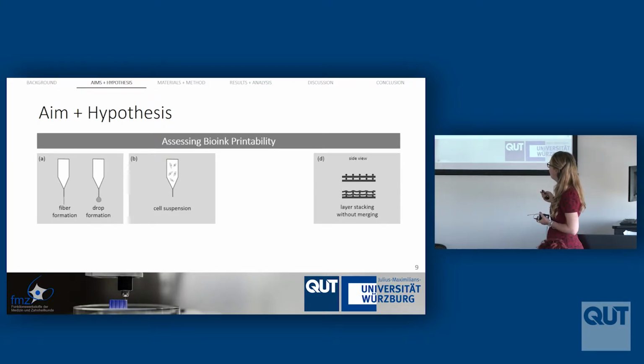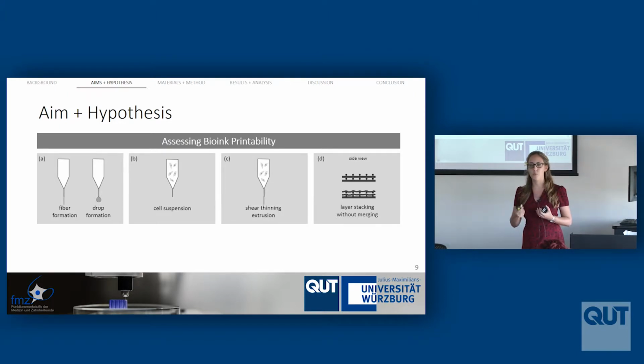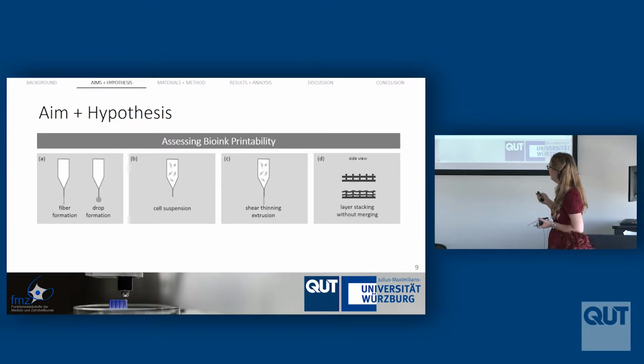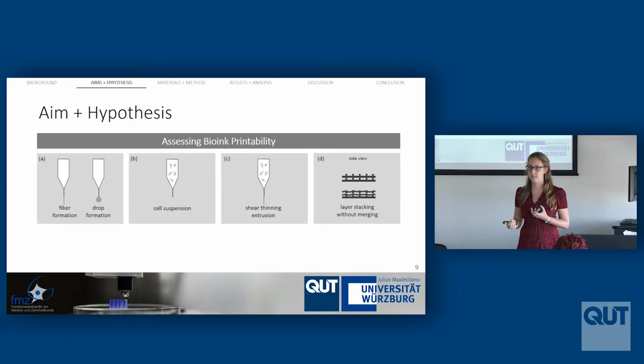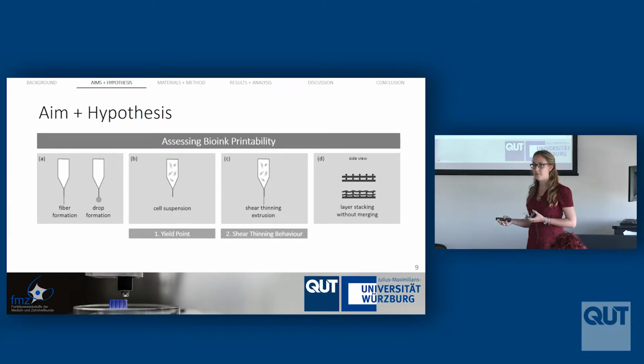And so a property of hydrogels is that they're shear thinning, and so this means that they get more liquid, so they get less viscous as you apply force to them. And so this is what happens through the needle. They start getting less viscous, and this allows the cells to move through the needle without being damaged, but then also be extruded into a fiber at the other end as well. And so the aim of my study was to characterize the yield point and the shear thinning behavior. So these are rheological properties of these materials, looking at their viscosity and their elastic behavior. Characterize these with some very simple, easy characterization techniques and be able to tell straight away whether our material will be able to be printable based on satisfying these conditions.